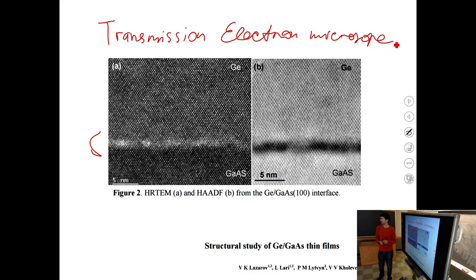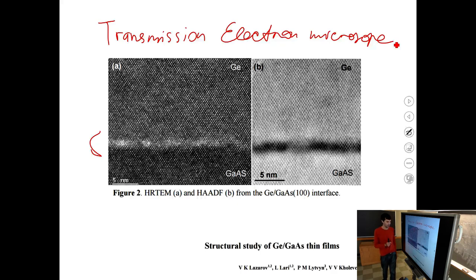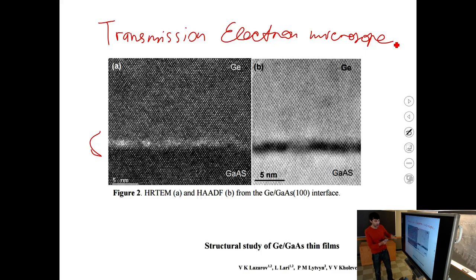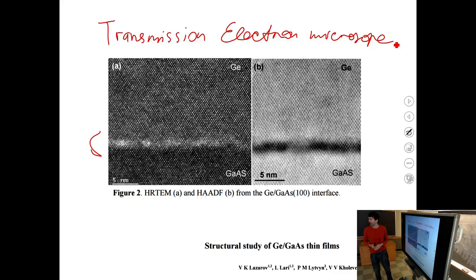The TEM sends electrons at very high energies — something like 300 kilovolts — all the way through the structure. The pixels you see in high resolution represent atomic rows, and this tells you about the crystallinity of the interface. If there are any defects, dots will be misplaced, missing, or shifted — that's called a dislocation. To my eye, these pictures show a perfectly grown structure.